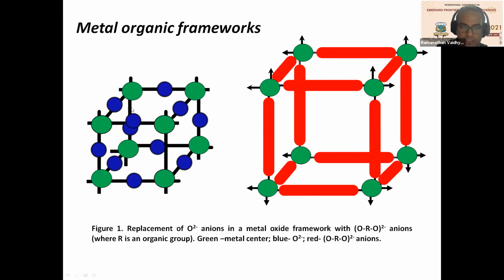Now, if you replace this oxide ion with a long organic linker, which again is a 2- charge species, and which can coordinate with the metal, you can simply expand this cube to a much larger size. And now this size becomes more suited for molecular sieving or molecular recognition. Okay, so that is where MOFs have attracted a lot of interest.